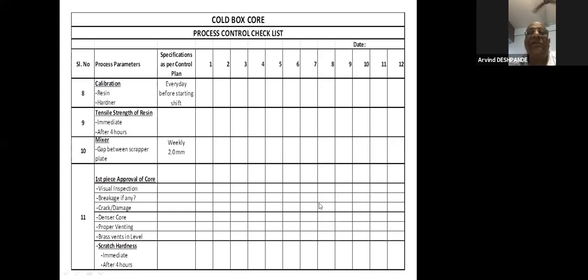Then tensile strength of resin, immediate and after 4 hours. So once the calibration of sand and additives is done, the tensile strength of the dog bone piece has to be checked immediately and after 4 hours. If variation is there, accordingly we have to do the correction. If it is less, then you may have to add binder. But this is the most important parameter of cold box core. Immediate, 4 hour, 12 hour, 24 hour. Records should be there, batch-wise.